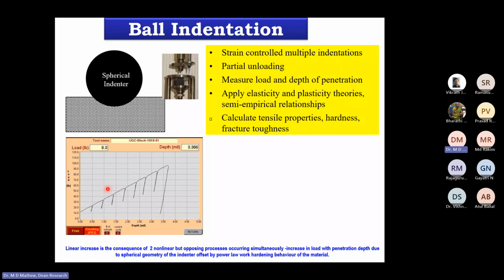What you see here is one ball indentation test. The x-axis is the depth of penetration, y-axis is the load. You see that you start here, so this is the depth of penetration, and then partial unloading. Again, you are increasing the depth, then it is followed by unloading, then again loading. So it is done, and after about 7 steps, once you have reached the preset value of total depth of penetration, the sample is unloaded.